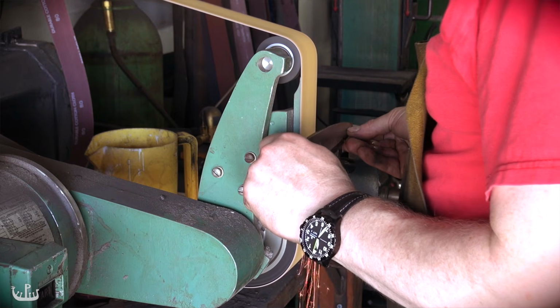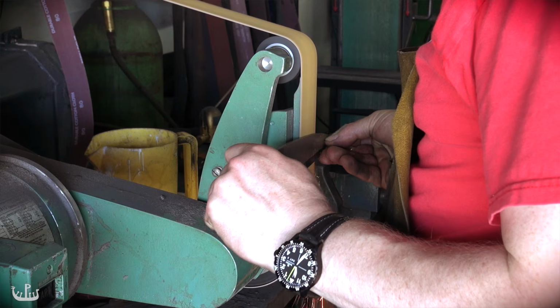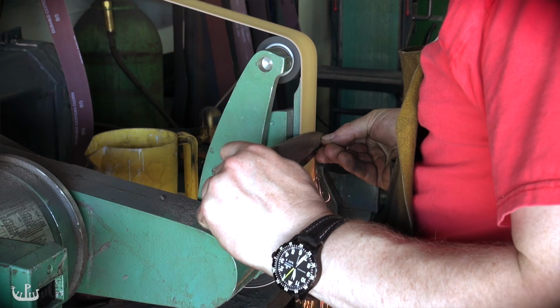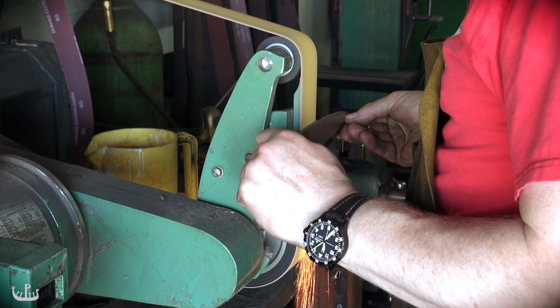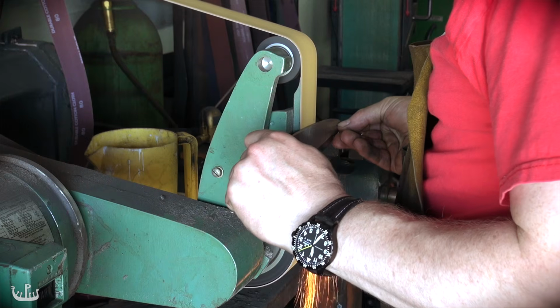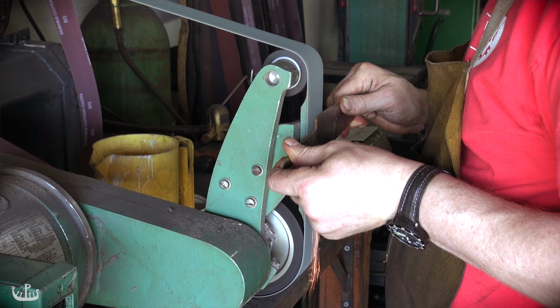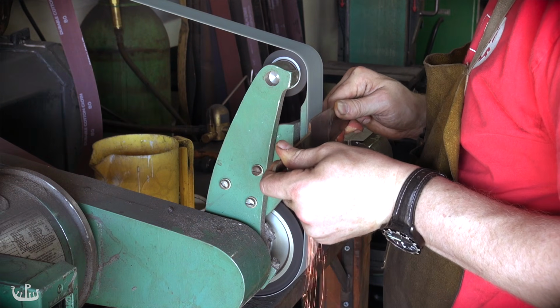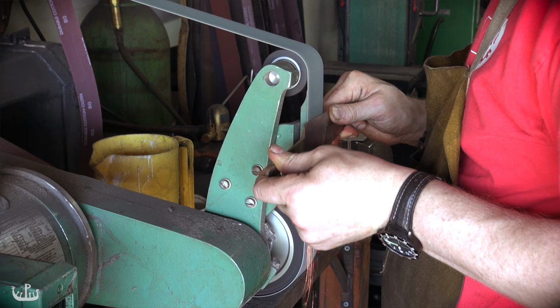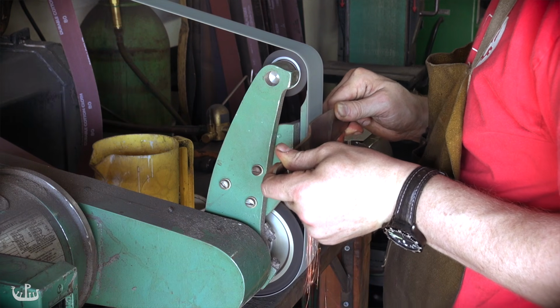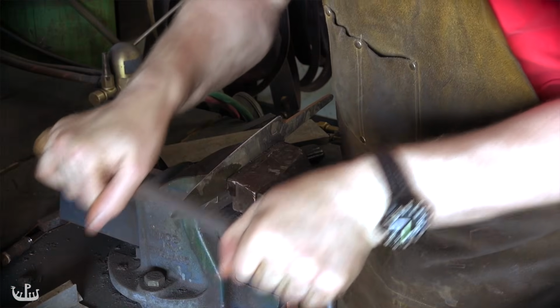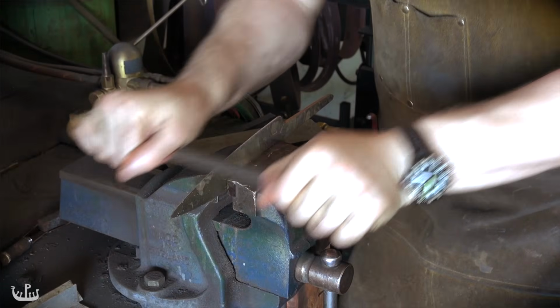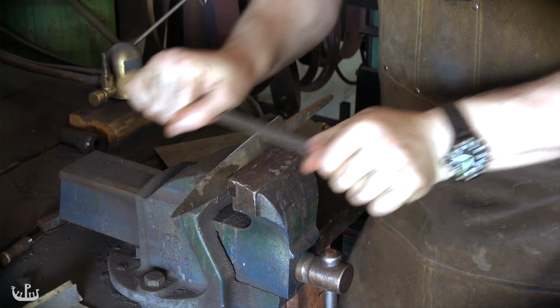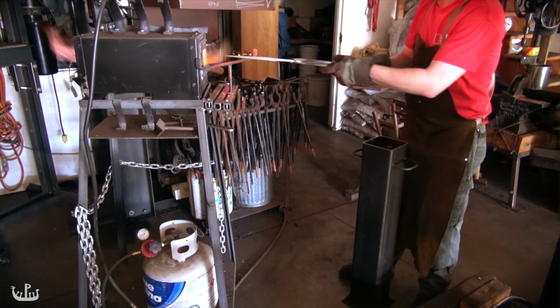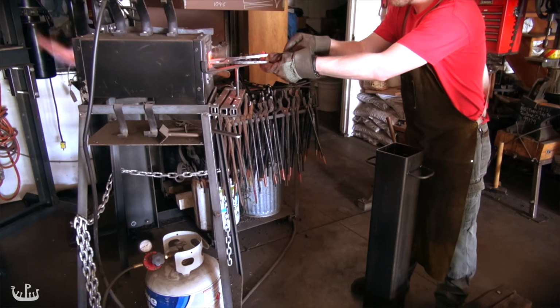Once the blade has cooled down, the final profile is created on the belt sander. First, the cutting edge is thinned by creating a flat grind. This takes quite some time due to the high carbon content of the steel. Before the heat treat, I remove all grinder marks as these may function as stress risers where the blade might crack.